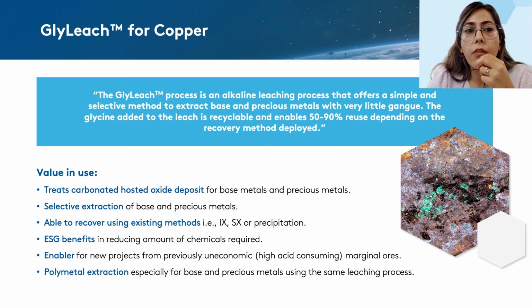There is some value in using glycine leaching technology for copper extraction, like treating carbonate-hosted copper oxide for both base and precious metals. Glycine leaching technology is a selective extraction method for both base and precious metals. It enables recovery using existing recovery methods such as ion exchange, solvent extraction, or precipitation. There are some ESG benefits like reducing the amount of chemicals, and it enables previously uneconomic marginal ores, the ones that use a high amount of acid. And it's beneficial for polymetal extraction of both base and precious metals using the same leaching process.